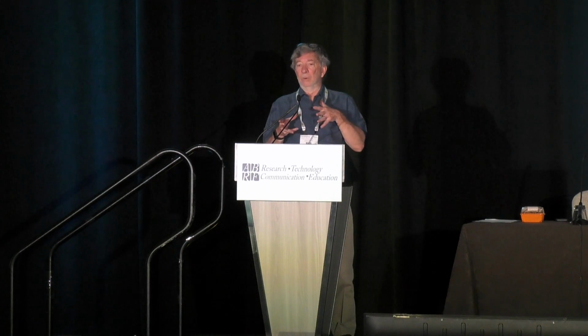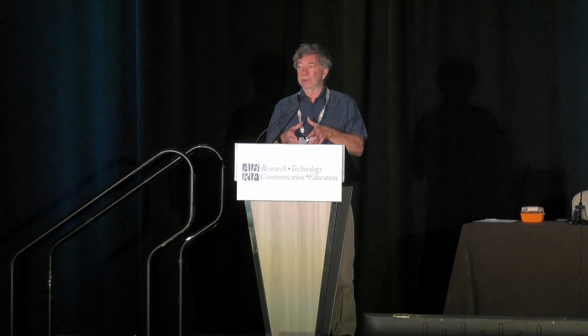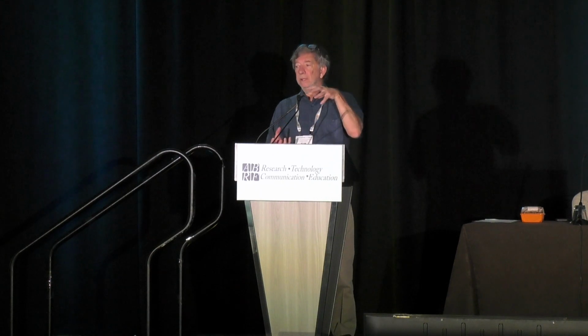Kirk also talked about the need for additional signal by putting heavy metals into samples to get good imaging, but that also has another factor for volume EM, which is you don't need to do the typical sputter coating that we would do for non-conductive SEM. But we've just heard from Nick's talk that you don't need to have that metal coating if you're using low vacuum SEM. So now we can put all of that together. We can do non-conducting volume EM by using low vacuum. There are some limitations with resolution, but we can then add in all of this additional spectroscopic data, crystallographic data, and make 3D maps. Nick just showed some meteorite examples.